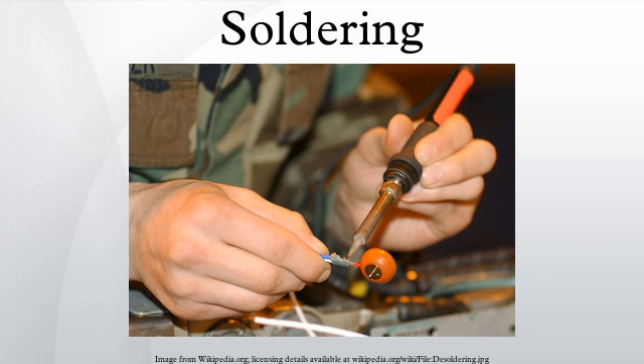A wire feeder is used to supply solder. Both lead-tin and silver-tin material can be soldered. Process recipes will differ depending on the alloy composition. For soldering 44-pin chip carriers to a board using soldering preforms, power levels were on the order of 10 watts and solder times approximately 1 second. Low power levels can lead to incomplete wetting and the formation of voids, both of which can weaken the joint.